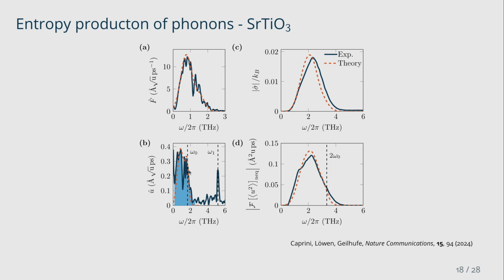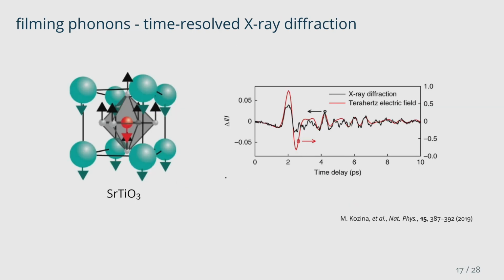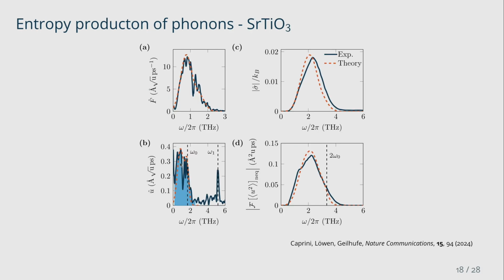And then the second thing is the phonon. You can take this picture and make a so-called Fourier transform, so instead of looking at the time scale, you look at the frequency of the oscillations that you see. Then you see very characteristic peaks, which are connected to very characteristic modes, plus some noise in the background. And we could show that if you put those two things together, you have a tool to read off entropy production in the material. It's a very interesting thing because entropy is a quantity which has been known for more than a century.